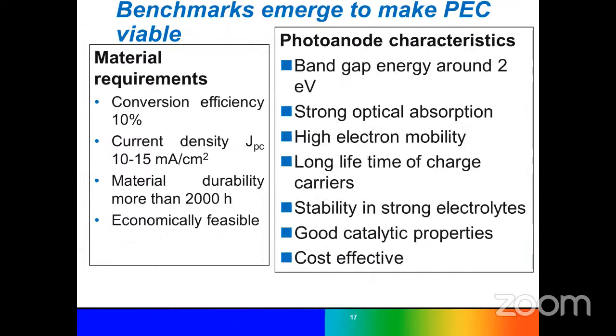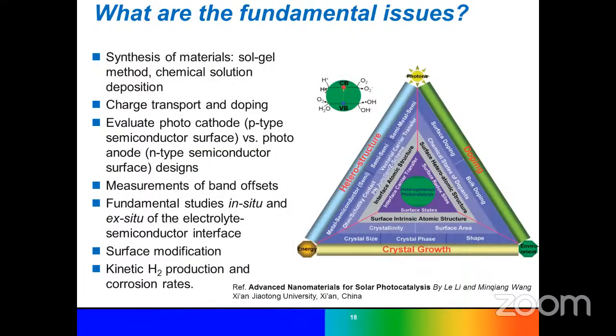So this benchmark we have to reach to get these devices commercialized. So here in the challenges in the systems, one is that we have to select strong optical absorption materials. High electron mobility should be there, long lifetime of the charge carrier, stability, good catalytic property, and cost. When we select a material, we have to remember these properties, and the material should introduce these types of properties to reach the benchmark of this conversion efficiency. So here, if you see, when we fabricate the photoelectrode, there are a lot of parameters dependent on each other. The photon, energy, and environment are all correlated.